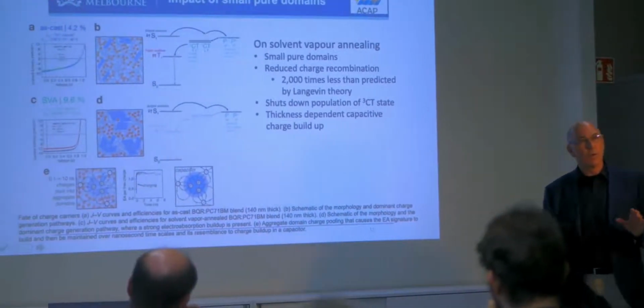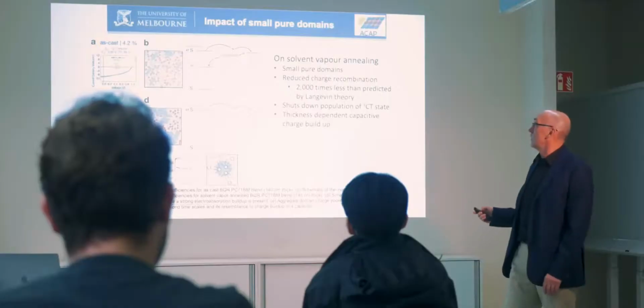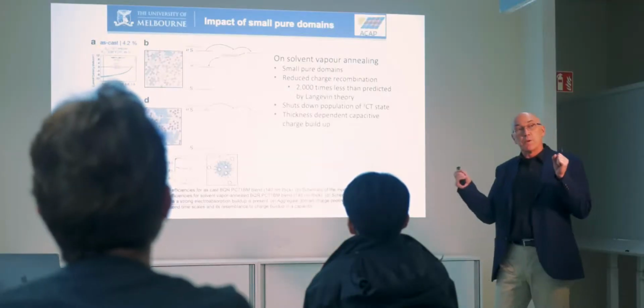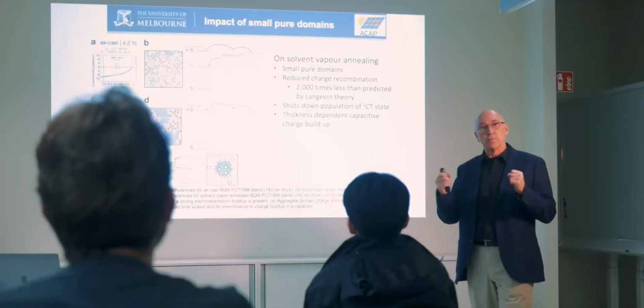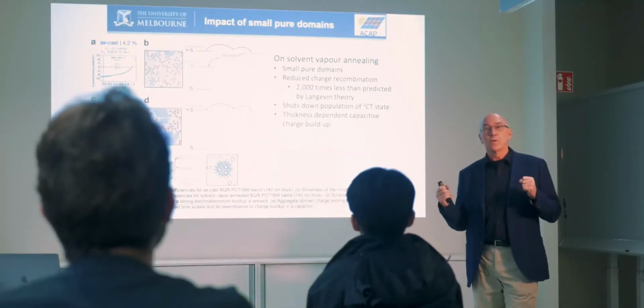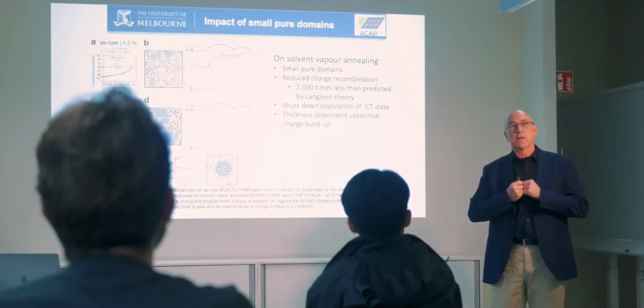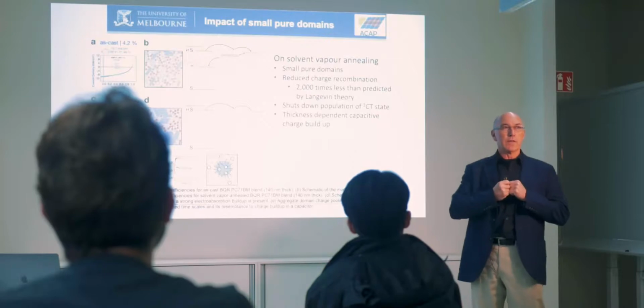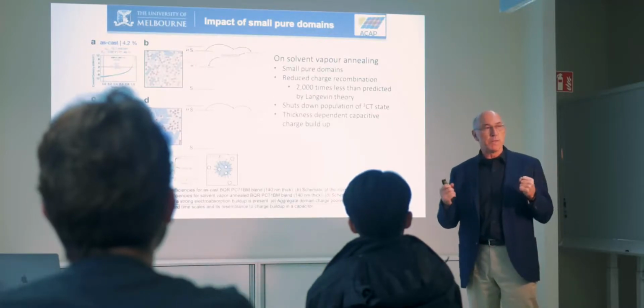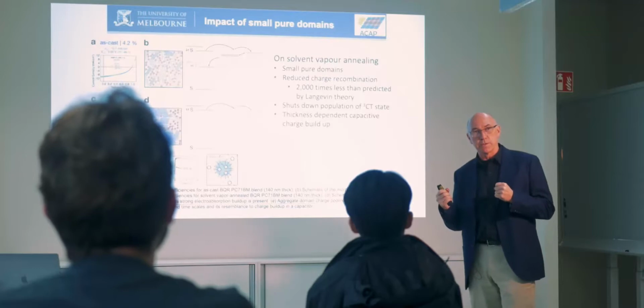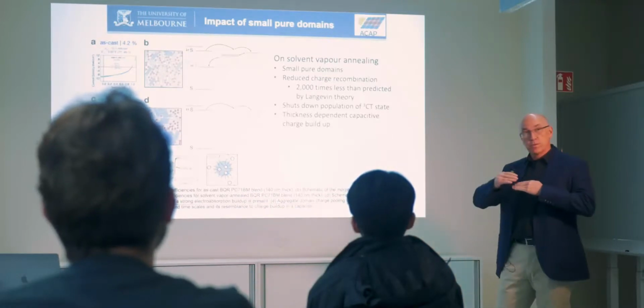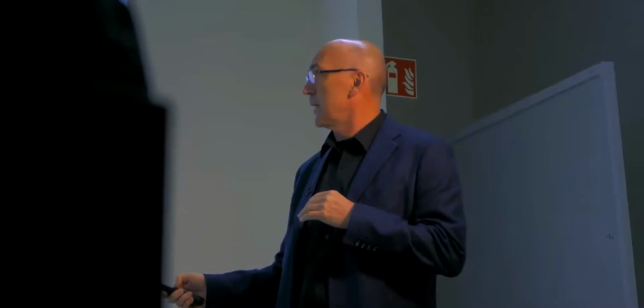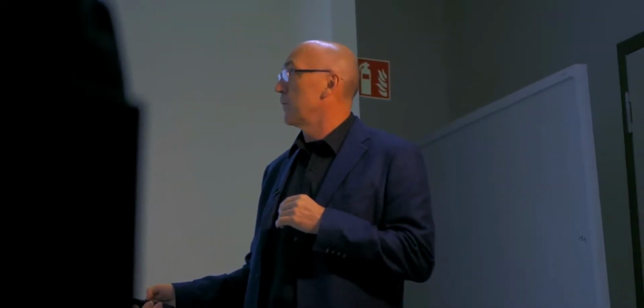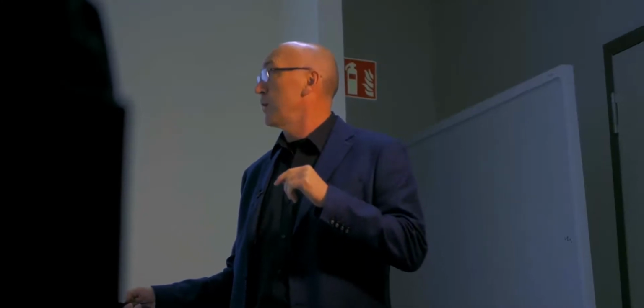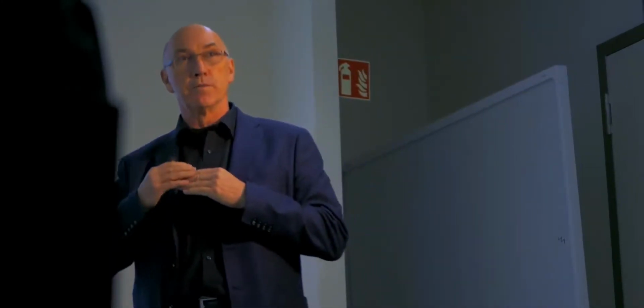And so when we look at this, and this is all the device work, small pure domains. But we can estimate what that charge recombination rate should be, and we are recombining 2,000 times slower than we should be. And so this is really unusual. That means we can get bigger numbers for our device efficiency. The other thing is that the thicker the device, and that's the data here, and you can't see it very well, but going from 90 nanometer thick film up to 320, we get a better device the thicker the film. And so we need to understand that.